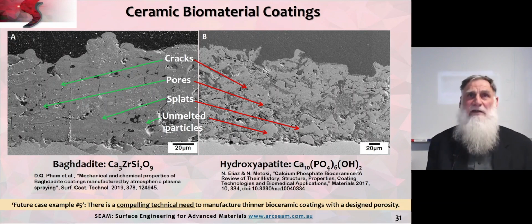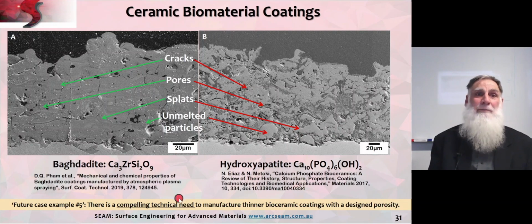The coatings that I'm showing you now are produced under conventional atmospheric plasma spray conditions with conventional feedstock. They are ceramic biomaterials that show the typical splats with cracks, pores, splats, unmelted particles, a material called Baghdadite, and the conventional hydroxyapatite. The orthopedic surgeons that use these coatings would really like thin coatings rather than thick coatings. Rather than having a coating which is 100 or so micrometers thick, they would love to have a coating which is integral and fully dense at a thickness of, say, 10 or 20 micrometers. So there is a compelling technical need to manufacture thinner bioceramic coatings with a design porosity that allows bone ingrowth.